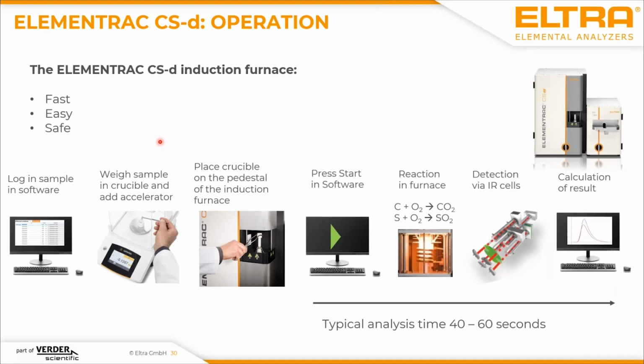How is it done? The operation is very easy. So what we need is the initial mass of our sample. Because it's a relative method, we always refer to the initial mass. You need a balance. You put your sample in the crucible, then you start the furnace via software, and then the crucible heats up. The gases come out. The carbon might burn, or the carbon might come out as CO2. Carbonate is decomposed by the heat inside your crucible. CO2 is coming out, and then you measure it in the infrared detection system, and the results are calculated automatically by the software.